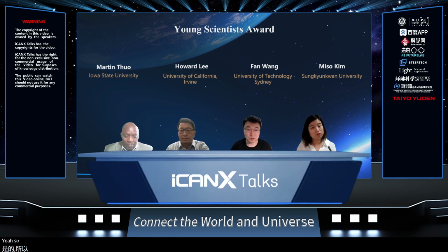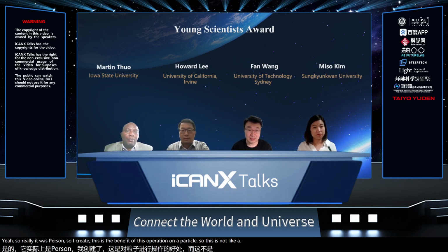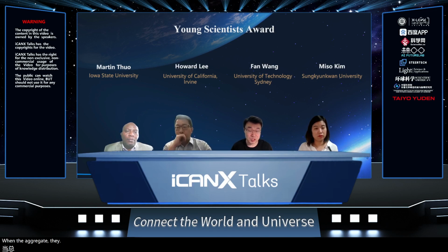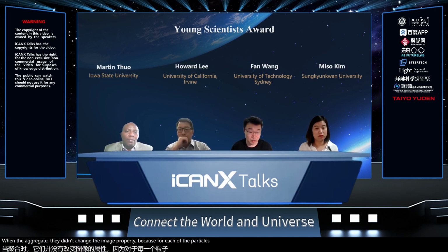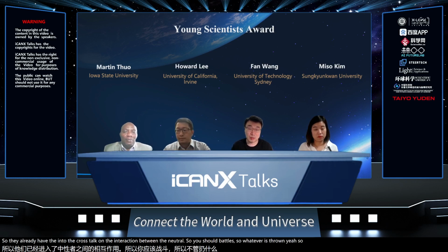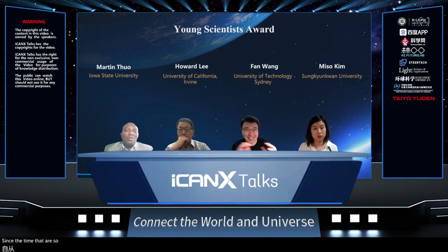Yeah, really good question. This is actually the benefit of this upconversion nanoparticle. It's not like a fluorescent dye that has some quenching. Even if you put some gold particles, you do have quenching, but when they aggregate, they don't change the emission property, because each particle already has a high density of emitters inside. They already have the crosstalk, the interaction between each of the emission dipoles. Each particle has 2,000 emitters and 4,000 sensitizers, so they are already bonded together. This is a good thing, and this is why it isn't affected by the surrounding material.